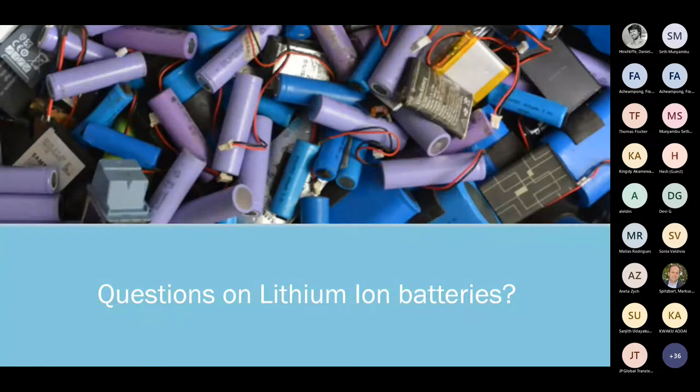What I have to emphasize here is that car batteries usually have a relatively high resale value. Therefore, reuse is always the first option. Only if reuse is not possible should recycling be considered. And recycling will always be done at module level. The battery always has to be discharged. So the typical process is removal of the module, discharging, and then the module is sent to recycling.